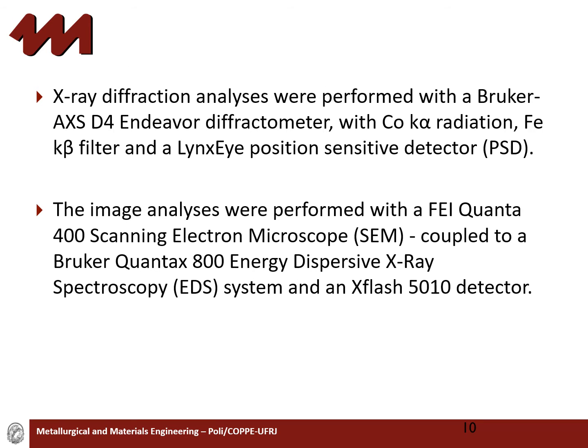The X-ray diffraction analyses were performed with a Bruker D4 Endeavor diffractometer with cobalt radiation, iron filter, and the position sensitive detector PSD. For the quantification of the minerals and the phases present in the ore, the Rietveld method-based mineral quantification with a fundamental parameter approach was used, in which the software used was Topas 5.0. The crystal structure information for the minerals was supplied by the Bruker structure database. The image analyses were performed with a scanning electron microscope coupled to an energy dispersive X-ray spectroscopy system and the detector.